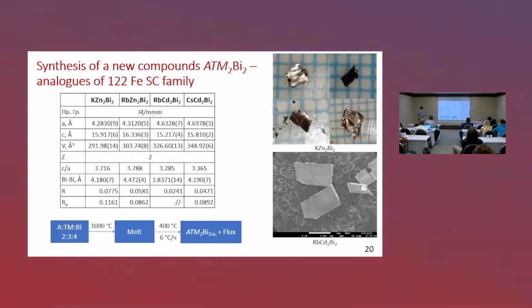And then we tried to prepare compounds with bismuth with an analogous structure, like 122. It's interesting that only one such compound was known before our work: barium manganese 2 bismuth 2. We used the flux method, and we prepared 4 compounds with the composition 122 and the structure of iron-based superconductors.